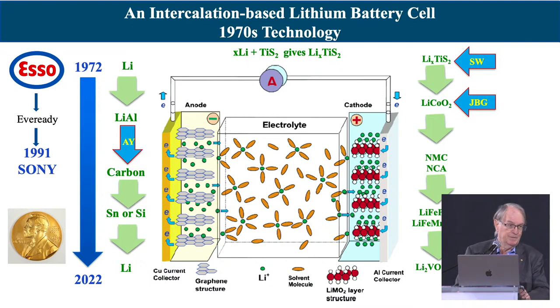But over these 50 years, we learned a number of things. One, lithium metal by itself is not the safest metal to use. Any of you who've done electrodeposition will know that metals tend to deposit as dendrites. Those are sharp, spiky things, and they then short out the anode and the cathode. So at Exxon, we switched to a lithium aluminum alloy, and this works fine for 10 or 20 charges.